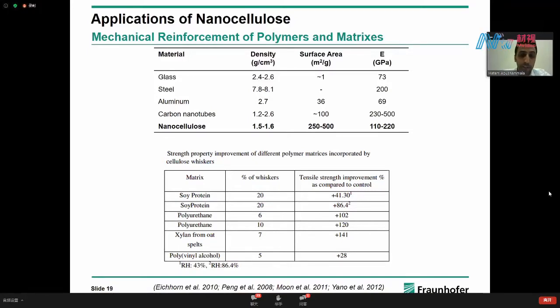Here, I would like to give you some examples of the effectiveness of nanocellulose. And here you can see the percentage of whiskers. These whiskers mean nanocrystals. This is the old name of nanocrystals. By putting in a few percent of nanocellulose, and I would say 20% here is really a lot, up to 5% is a logical amount. With up to 5%, you can get an improvement of 50 to 100% in mechanical properties. And this is really a big improvement.